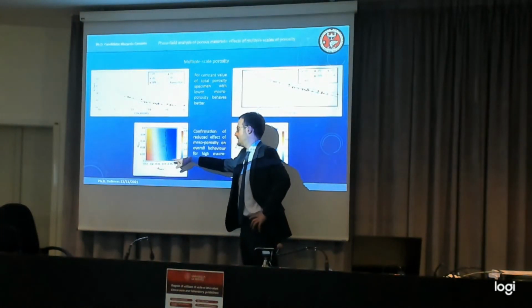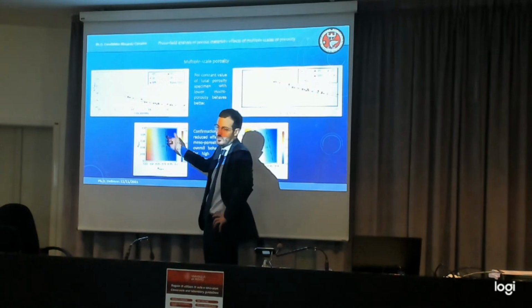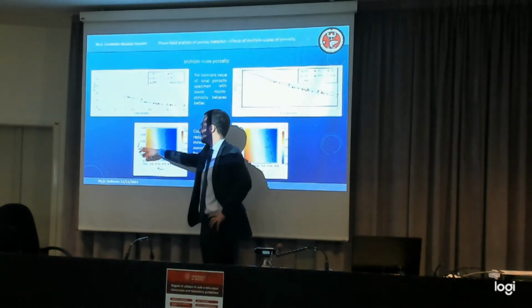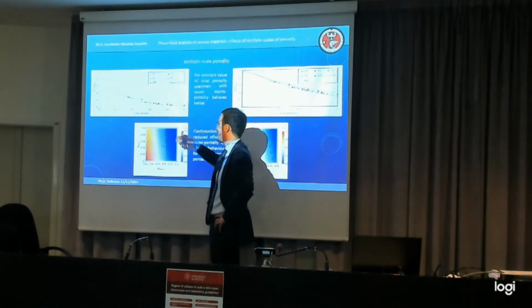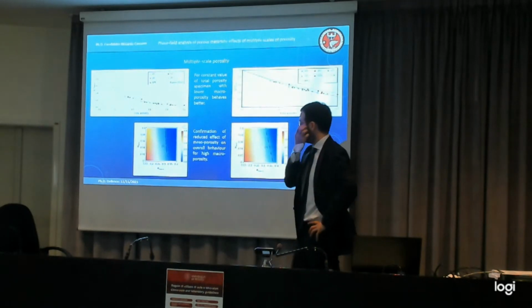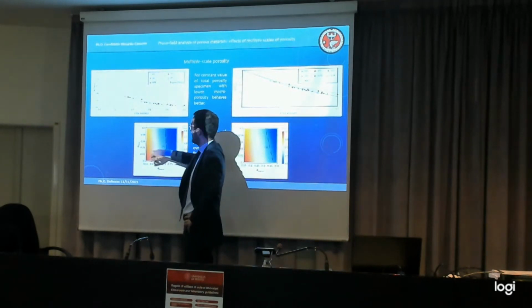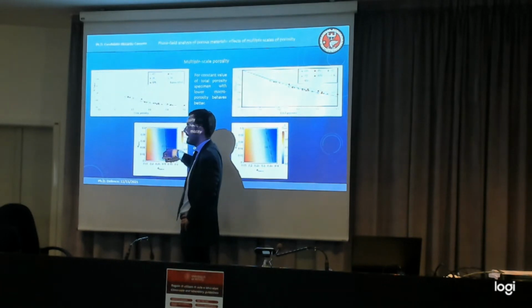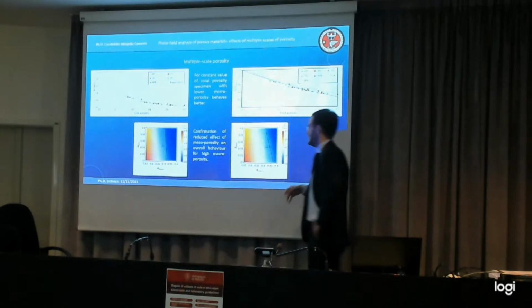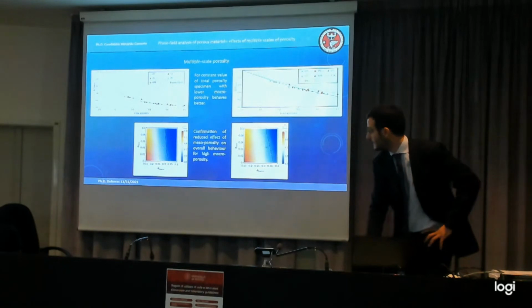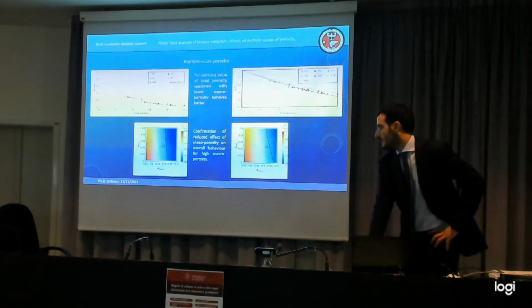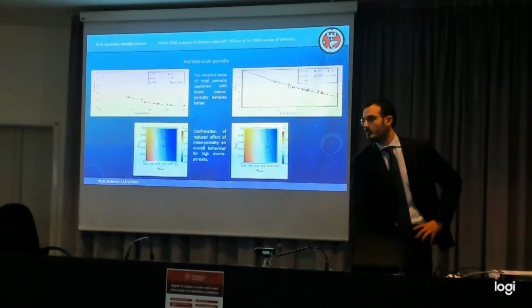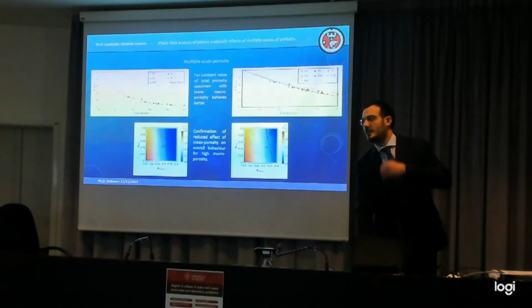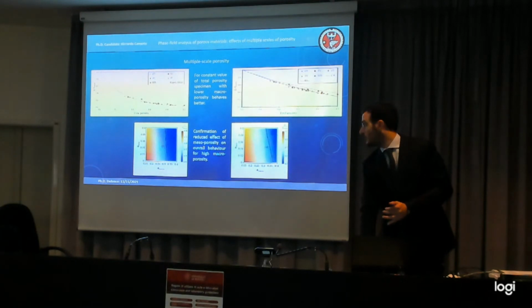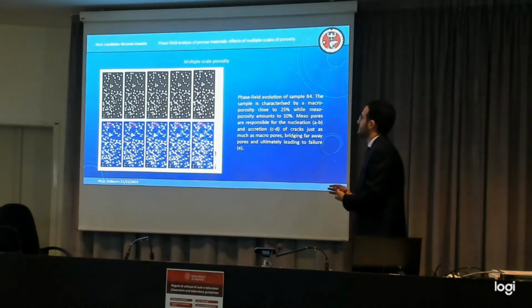We have seen that there is a nonlinear correspondence, obviously, with the scale of porosity in terms of strength and stiffness. And interestingly, if you increase the microporosity over a certain level, you don't get any significant changes in terms of strength. Meaning that the fact that small pores are inside the model already detriments the strength of the material in a irreversible way. Okay, and this is the phase field prediction.